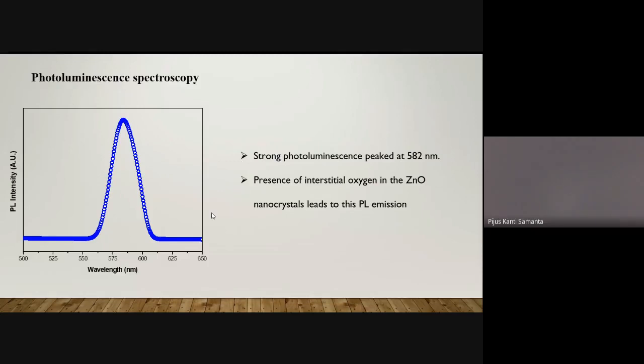The defect energy states have already been calculated by many researchers, and from their data we can see that this emission can be correlated to the existence of some interstitial oxygens in the synthesized zinc oxide crystals.